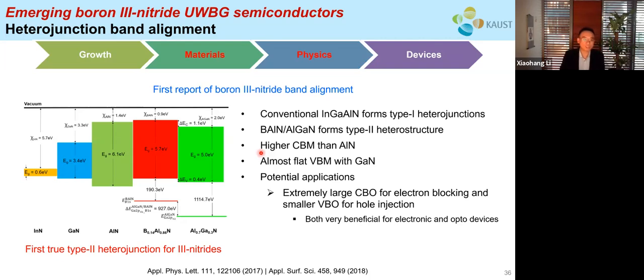In our studies, we have also conducted research on the heterojunction band alignment of boron III-nitride materials. Unlike the conventional indium gallium nitride materials, which always form a type 1 heterojunction, we found that, interestingly, by adding boron into aluminum nitride, not only does the conduction band minimum, where you have the free electrons, move up, but the valence band maximum, where you have the free holes, also moves up. So this forms a very interesting type 2 heterojunction, right? This is very significant because you can then combine type 2 with type 1 to improve existing devices or to invent new devices.